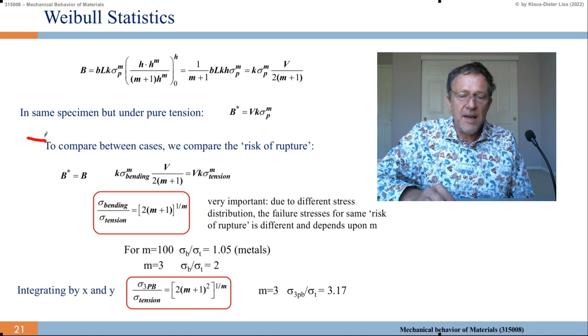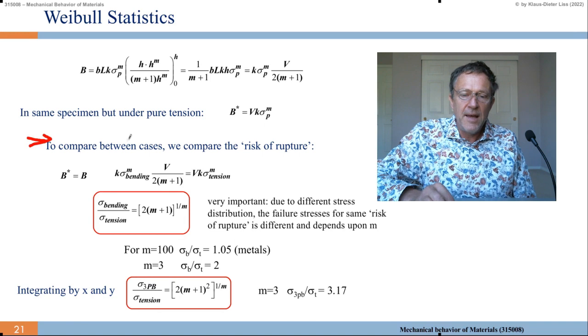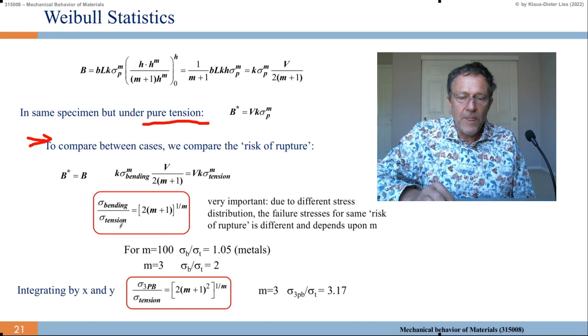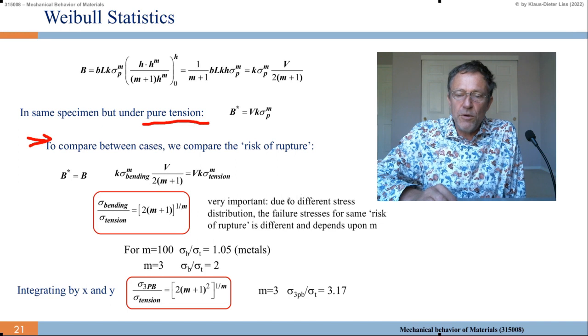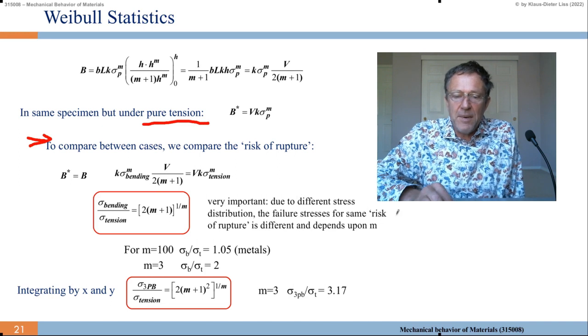So to compare between the two cases, the risk of rupture of the bending and the pure tensile experiment, let's say this probability of failure we put equal, then it works out the sigma bending divided by sigma tension scales by the factor 2m plus 1 to the 1 over m. So this is very important. Due to different stress distributions, the failure stress for the same risk of rupture B is different and depends upon m. Yeah? It depends on m. If m is very large, 1 over m goes to 0, then that goes to 1.